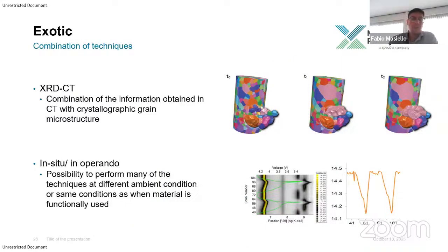And then, for the exotic techniques, something that is coming more and more, also at the lab scale, is the combination of information. For example, XRD CT is a combination between CT and XRD. So you not only get information on the 3D structure of your sample, but you can also get information grain by grain on the single grains by using X-ray diffraction combined. That's something that is now available in lab scale instrumentation. And I mentioned it briefly before, but there is the possibility to perform many of the techniques that we mentioned before, both for X-ray scattering as well as fluorescence, in operando or in situ, for example at different temperatures and different conditions.